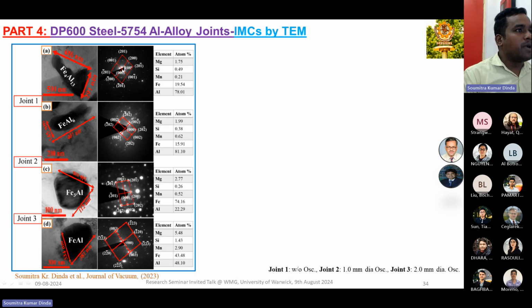So if this is my point, the nearest point is 001 bar, and the second nearest is 200, and the angle between these two is 1.08. And from the literature, we can find out this is for this type of compound, that is Fe4Al13. And we also did the EDAX when we put the EDAX detector on this particular particle. So similarly we did it for all cases, and we found that all 4 compounds, Fe4Al13, Fe2Al5, Fe3Al, and FeAl, are found in all cases.